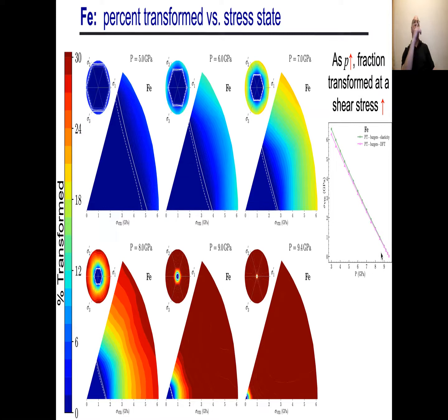So one of the things you see right away is the transformation pressure is very shear dependent, or the shear that you need to apply to get the transformation is very pressure dependent. Either way. And the reason is quite clear, because in iron, if I look at the BCC to HCP transition, the volume difference is substantial, and that volume difference is what gives you the pressure effect.